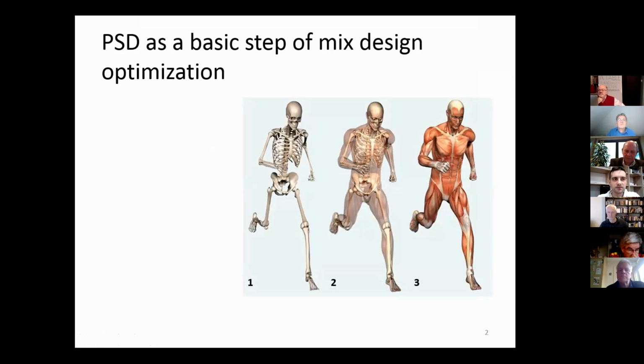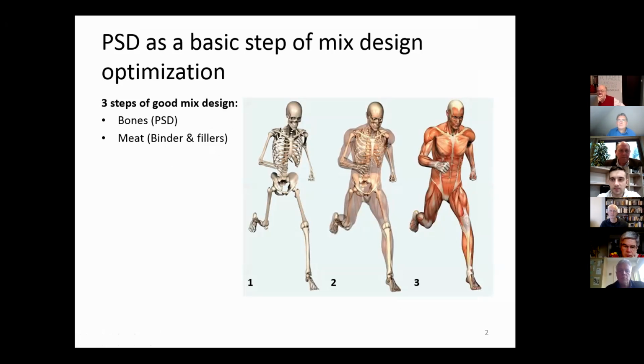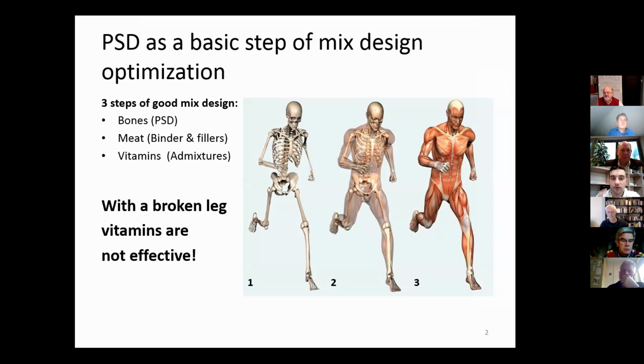Usually, I explain the mix design in a very simple way. I compare it with the human body. Firstly, we should create the bones, the so-called granular skeleton. Then we put some meat on it, which means binder and fillers, and then salt it with some amount of vitamins, admixtures. And this gives the concrete some superpower. But my very clear message to you today, as a founder of a Ukrainian admixtures company, is that with a broken leg, vitamins are not effective. If you have to fix something, you should first look at the granular skeleton and start your mix design from the granular skeleton.